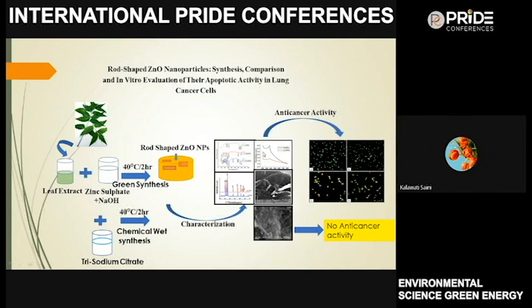These particles have been used for anti-cancer study, in vitro study of the lung cell line, and these are the apoptosis of the cell line. And when we used the same particle synthesized by the chemical wet method, in which we used 200 millimole trisodium citrate, 1 gram sodium hydroxide, and 0.2 molar zinc sulfate, then the powder XRD is here, and FTIR is here, and UV is also here, and the morphology is this, but this particle doesn't show any induced apoptosis.